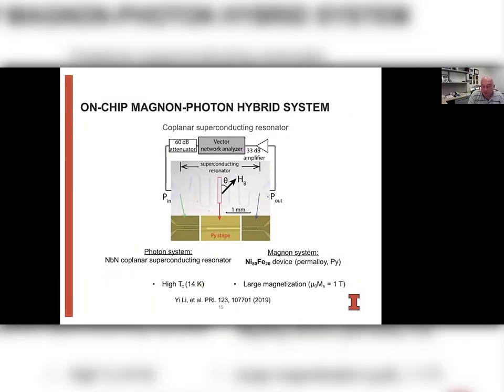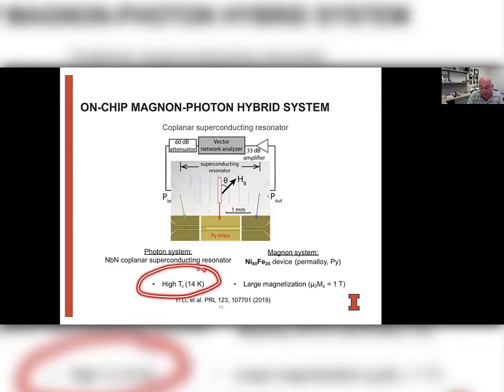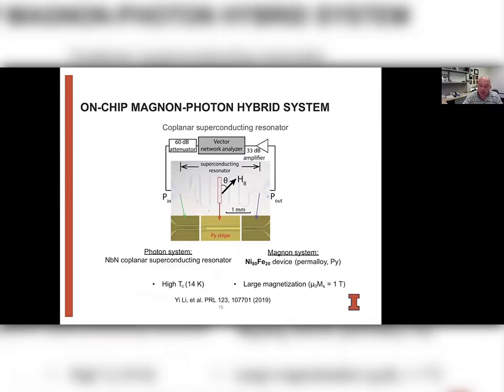Now, for the photon system, we built the photon system based on niobium nitride. And we chose niobium nitride because it has a fairly high Tc, 14 Kelvin, which means that it also can tolerate higher microwave photons than what you typically have in a superconducting system. So it allows to go to higher frequencies.